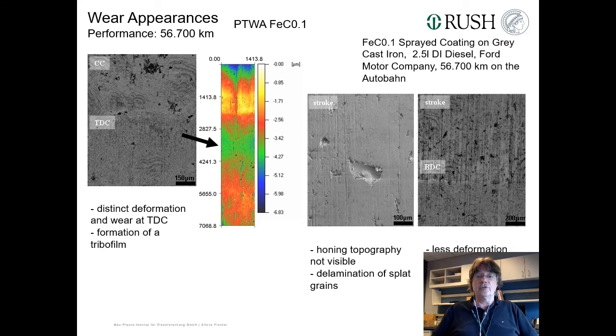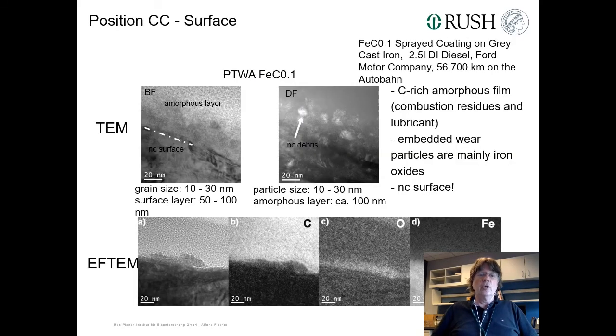The top dead center is of high interest. Certainly, we start with the combustion chamber because we found a strain gradient and a nanocrystalline material as well, which has been generated, we think, by these explosive stresses, some sort of impact wear, I would say, by the gas itself. You find some amorphous stuff. You find remains of everything that has been there in the combustion chamber and burned into soot or hammered into the surface, oxides, everything.